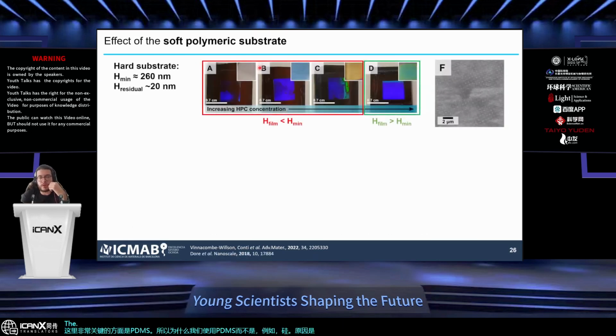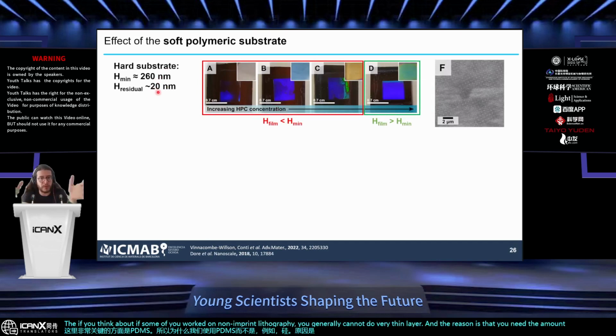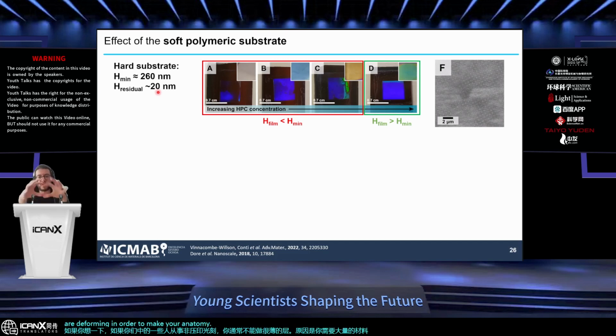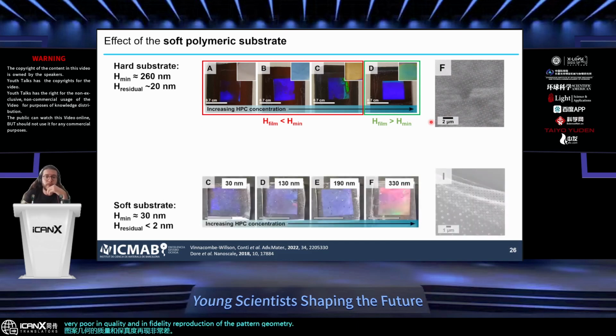if some of you worked on nanoimprint lithography, you generally cannot do very thin layers. The reason is that you need the amount of material that you are deforming in order to make your nanoimprint to be able to occupy the entire volume of the stamp. So if I try to do a very, very thin layer, my stencil will be very poor in quality and in fidelity of reproduction of the pattern geometry. However, if we use a soft substrate, we observe that we could make the HPC stencil as thin as 30 nanometers.